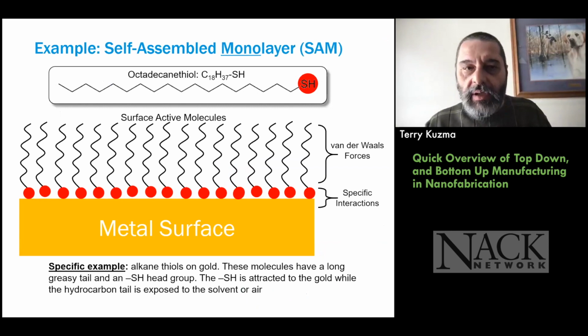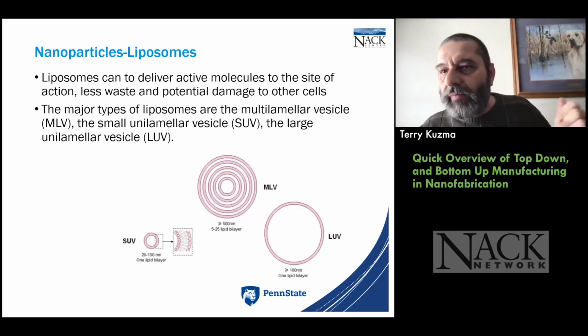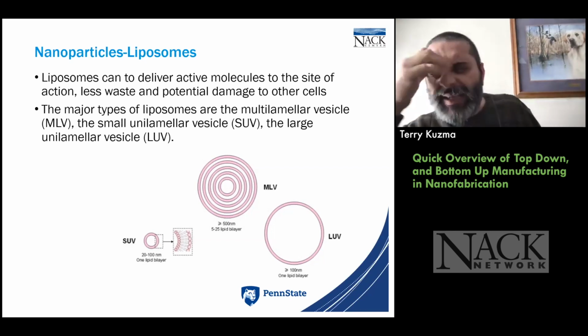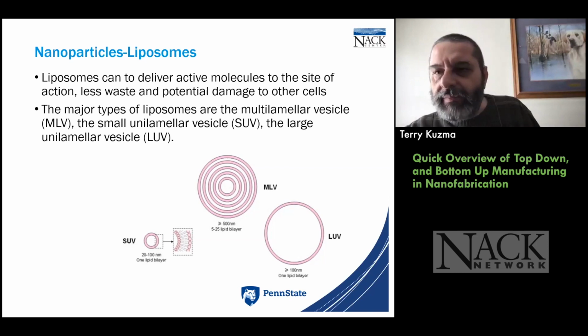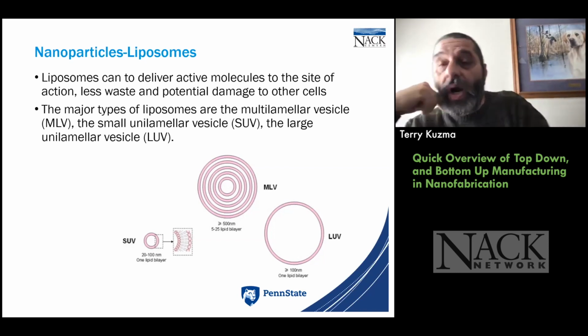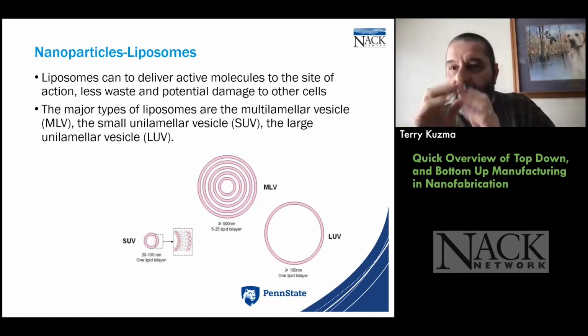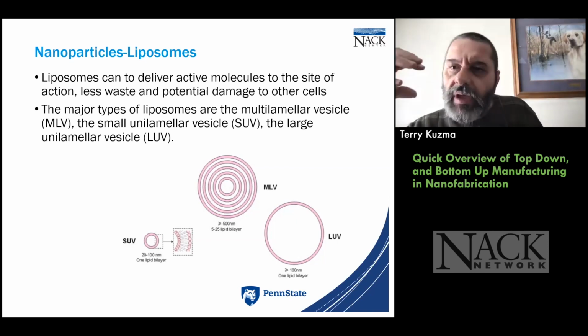And what I'll get is, oh, I'm done. I don't have that extra picture. What I'll get is I'll get all SUVs. And I think that it takes 7 passes or something. And then you'll have like 95% of that thing. You just can't do it in one. But if you did like 7 or 11 passes, then you're going to have a really good sharp peak Gaussian distribution of that population. And you have to, because when you give this as a drug, that's a controlled dosage.